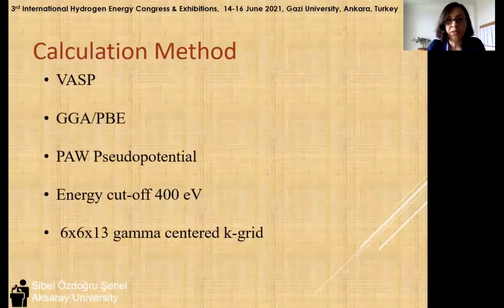All calculations were carried out using the Vienna Ab initio Simulation Package. For the generalized gradient approximation exchange correlation energy, the Perdew-Burke-Ernzerhof parameterization was used. The eigenstates were expanded into plane wave basis functions, and the ion cores were represented with the PAW pseudopotentials. The kinetic energy cutoff was set at 400 electron volts. A 6 by 6 by 13 gamma-centered k-point grid was used to sample the Brillouin zone.